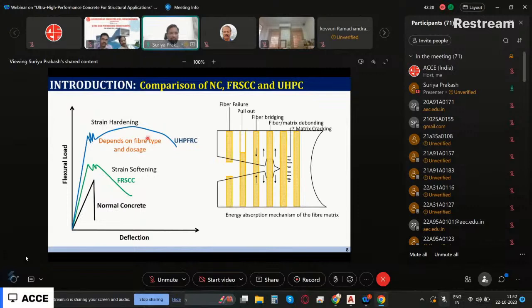Okay. Now, how do we get this kind of strain hardening behavior? If you look at how these fibers work, all these yellow colors are basically fibers. The moment it cracks, these fibers will arrest the crack. Especially in the vicinity of the crack itself, when the matrix is cracking, first of all, it will delay the cracking. Even the origination of the crack will be delayed to an extent. Then the fiber will start debonding initially. And then after a certain point of time, the length of the fiber is very short, so the fiber can pull out also.